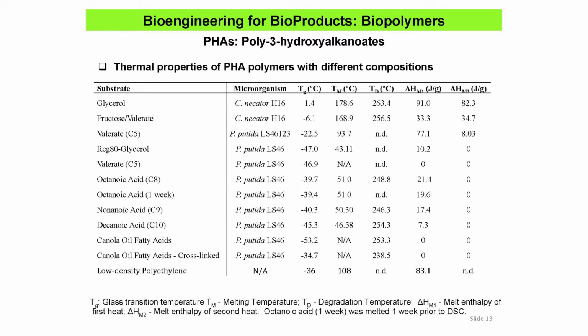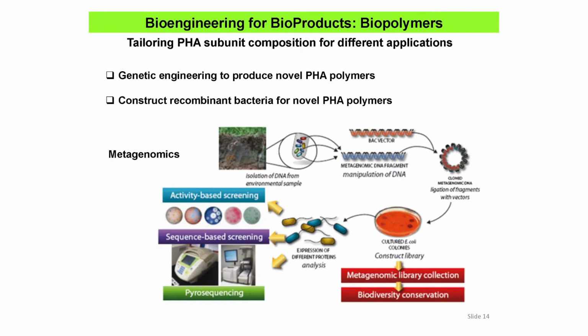It's got the same properties. But for some of these polymers, if you melt it and let it re-solidify, it doesn't come back to the same level of crystallinity and solidity that it had before you first melted it. So the second melt takes less energy, for example. Okay, so for example, 77 versus 8, right? Because it doesn't really crystallize, or it may take a longer time to crystallize. So these are some of the properties that we have to think about when we're trying to make polymers that can substitute for petroleum polymers, for example.